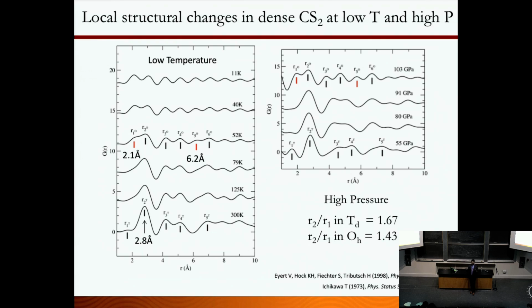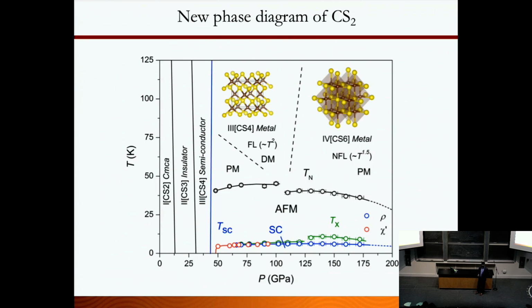So I was telling you, when you apply pressure, one thing that happens under pressure is the coordination increases. To adapt to a higher pressure environment, you increase the coordination. So the carbon disulfide, to start with, is 2-fold coordinated, but under pressure it goes to 3-fold, 4-fold, and even 6-fold. Interestingly, all this material that we form is stable. We can bring it down to ambient condition and it still has the metallic properties, but not superconducting.